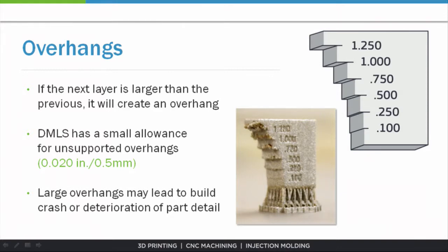And so we start to see damage on any surface less than 0.5 millimeters. So 20 thou of an inch or less is really the allowable overhang. As you get above that, as you can look on the chart there, you start getting into an inch, 1.25 inches, you get total build failure. So our rule of thumb is that you should design in 20 thousandths of an inch or less overhang feature on your parts. Otherwise, they're going to require supports, and you'll be adding cost.